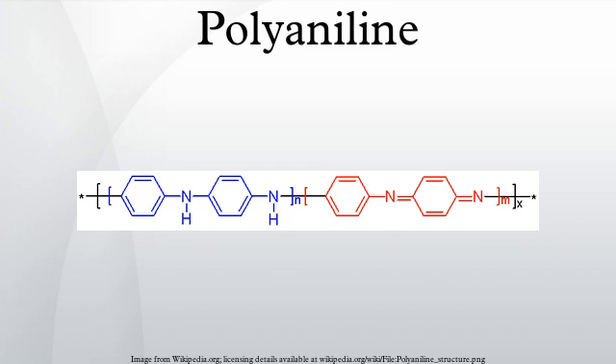The synthesis of polyaniline nanostructures is facile. Using special polymerization procedures and surfactant dopants, the obtained polyaniline powder can be made dispersible and hence useful for practical applications. Bulk synthesis of polyaniline nanofibers has led to a highly scalable and commercially applicable form of polyaniline that has been researched extensively since their discovery in 2002. A multi-stage model for the formation of emeraldine base is proposed. In the first stage, the pernigraniline salt oxidation state is formed. In the second stage, pernigraniline is reduced to the emeraldine salt as aniline monomer gets oxidized to the radical cation. In the third stage, this radical cation couples with the salt.